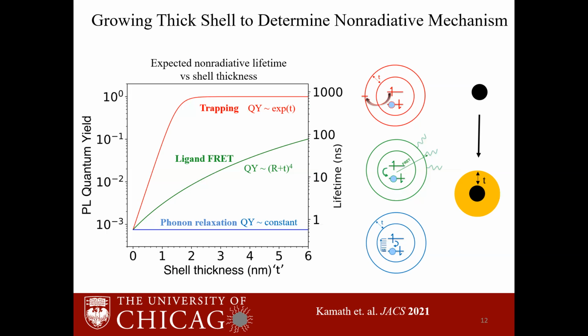If you're asking why we feel it's not phonon relaxation: we see this exponential decrease of the quantum yield because of ligand absorption, and that length scale will be around 3000 wave numbers, which is the CH stretch. But if phonon relaxation is the dominant relaxation, then that scale should be the phonon frequency, around 50 wave numbers. So we would see a very strong dependence of the quantum yield on the frequency of the excitation, and that's something we don't see experimentally. Also, if it's limited by phonon relaxation, then we will see a very strong temperature dependence, and when we cool our quantum dots, we do not see that either. So those are two reasons why we feel it's not phonon relaxation.